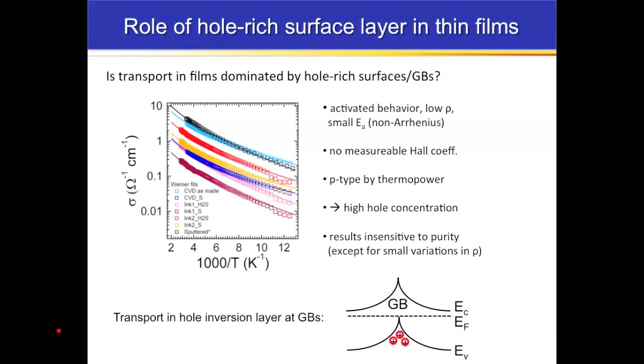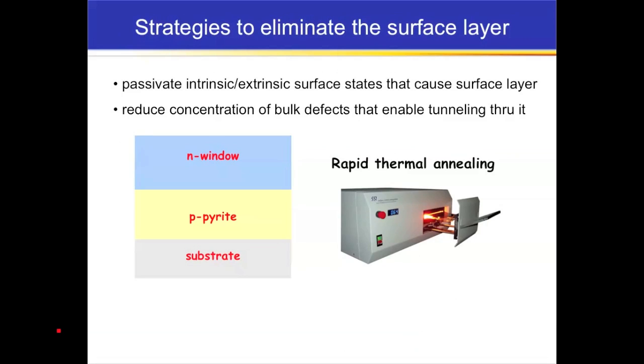And so this inversion layer could be the universal explanation for why the single crystals behave the way they do and why people have been seeing P-type material dominating in the thin film. And also why thin film pyrite-based materials don't work, because you don't get a very good photo response at all. So how do we actually correct this and prevent this, overcome this surface layer?